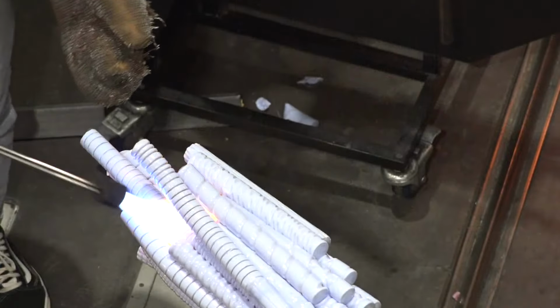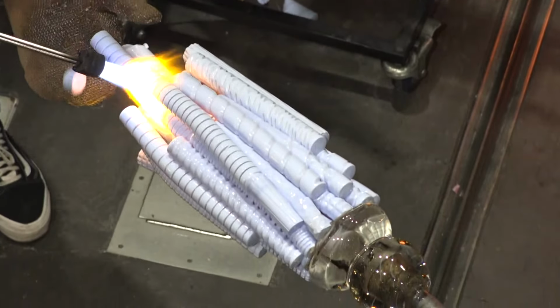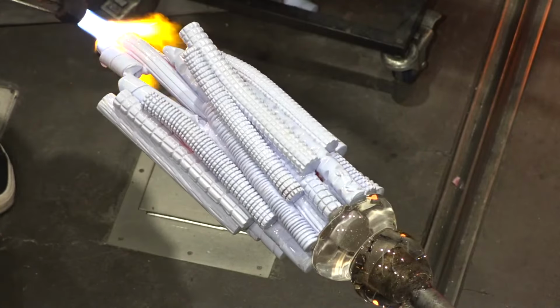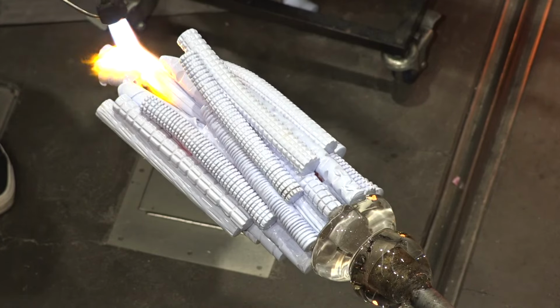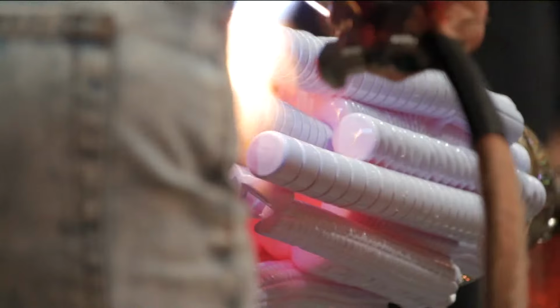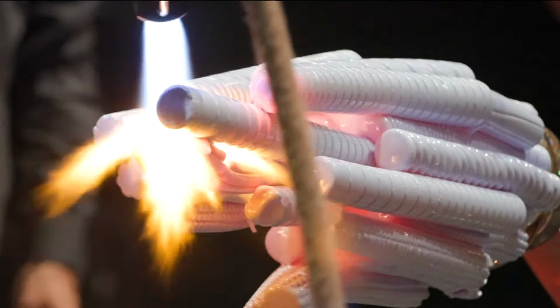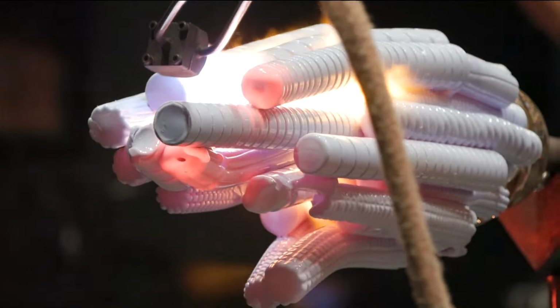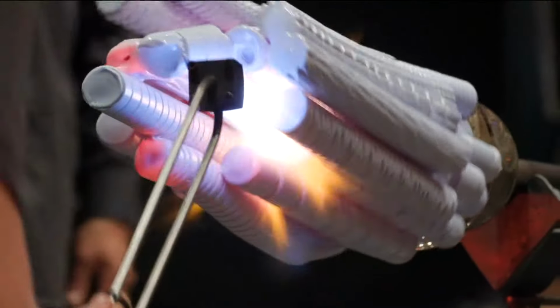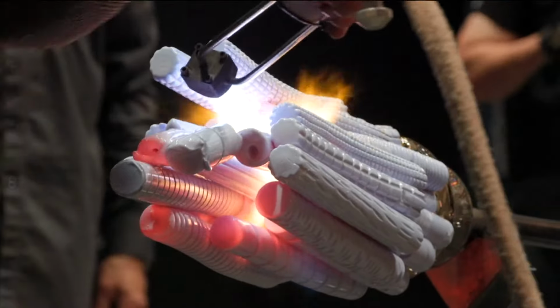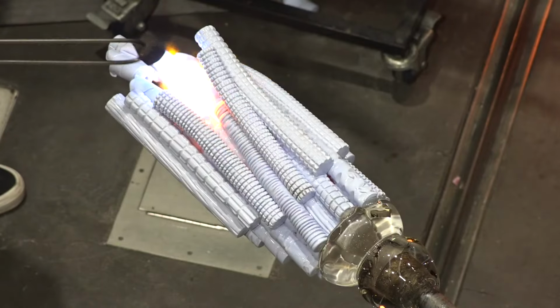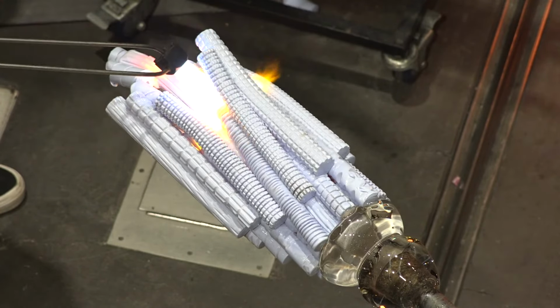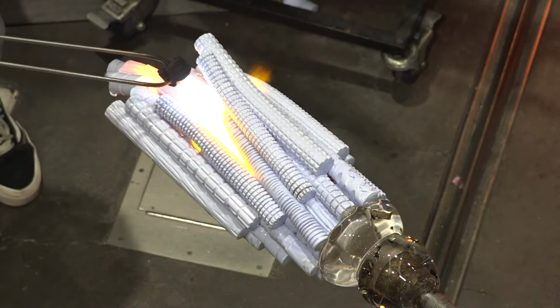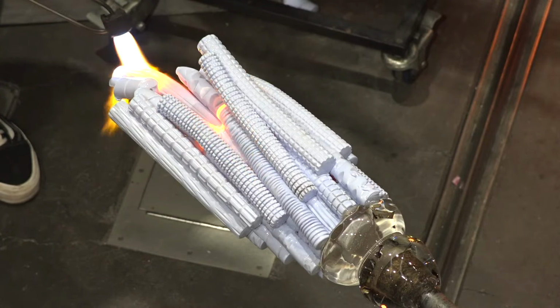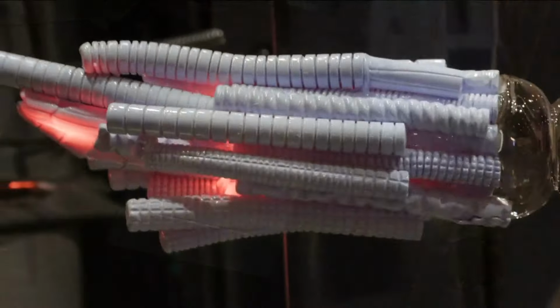Okay, great. Good questions online are about, some of us are seeing that these rods are being placed onto the vessel and then they're breaking in the reheating chamber. That happens. It's not ideal. But what's happening is when you put glass from a 1,000 degree oven into a 2,000 degree oven, that temperature jump is pretty drastic for glass, and sometimes the rods can break and crack because of the thermal shock.